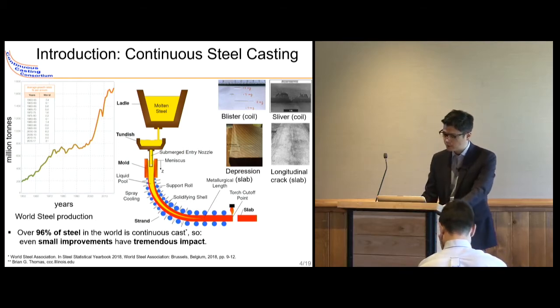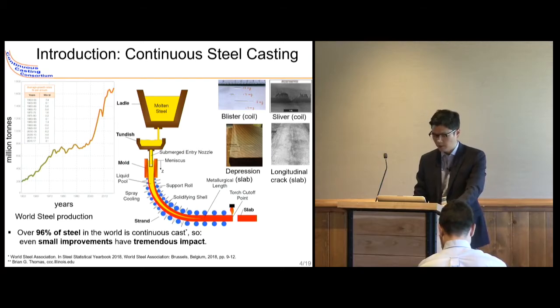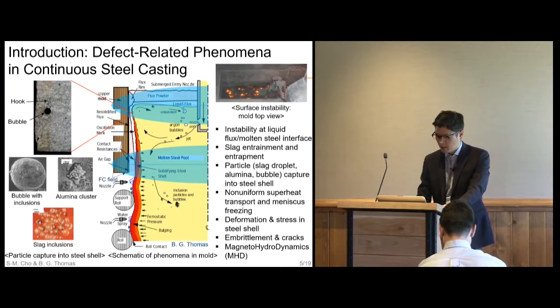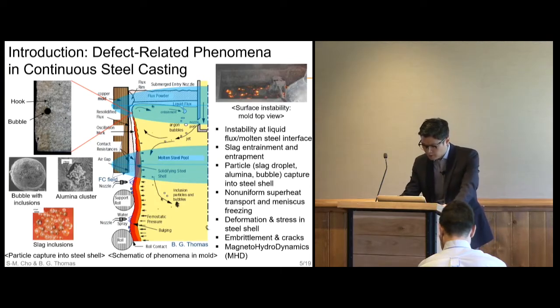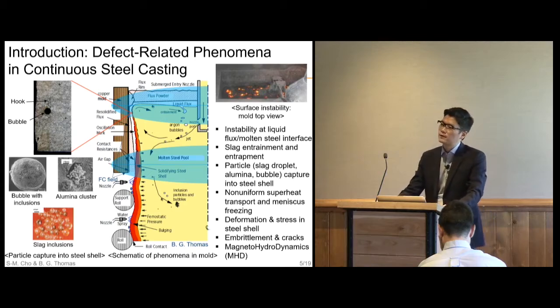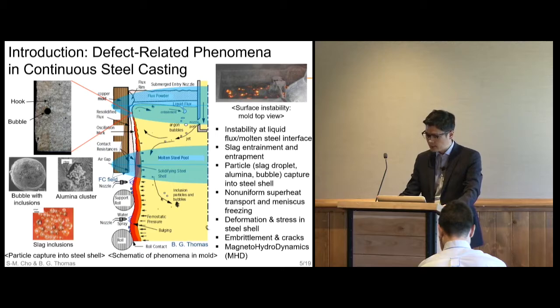In the next slide, we show more details about the defect formation phenomena. The center schematic view shows the various phenomena in a casting mold. These phenomena should be understood and controlled correctly to reduce the defect formations. Instability at the liquid mold flux and molten steel interface near the meniscus can entrain or entrap the liquid mold flux, which can result in surface or internal defects on the final steel products.